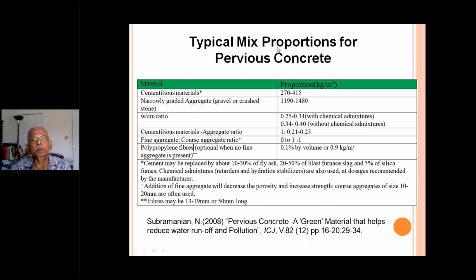As I told, the mixed proportion is very important for any concrete. So these are some of the mixed proportions which I have collected from different publications. The cementitious materials can be from 270 to 415 kg per meter cube. So what I mean by cementitious material is the cement may be replaced by 10 to 30% of fly ash, 20 to 50% of GGBS, and 5% of silica fume. Of course, chemical admixtures are also used, so the dosages are recommended by the manufacturer.